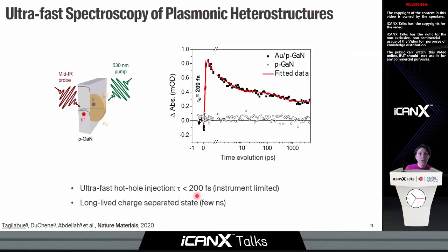Subsequently, we wanted to go a little bit deeper to understand better the details of this metal-semiconductor interface and the injection process of the holes. So we realized an analogous sample where we now have, in large area, gold nanoparticles onto the p-type gallium nitride, and we perform ultrafast spectroscopy measurements.